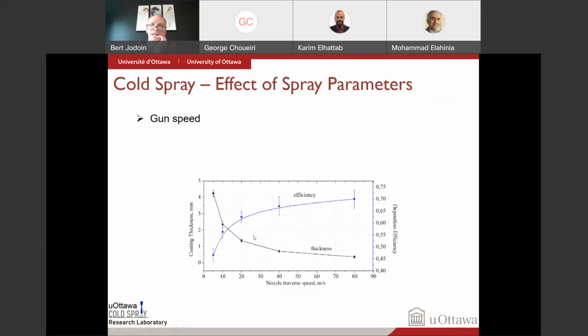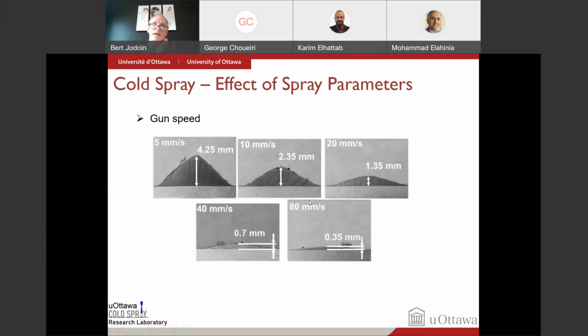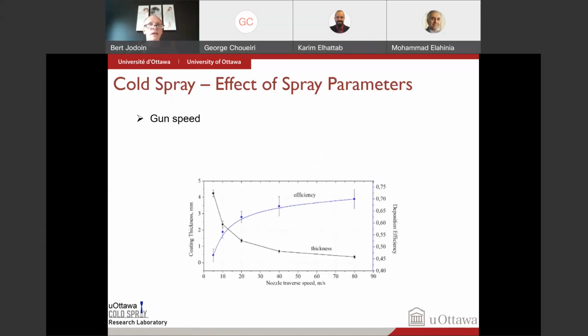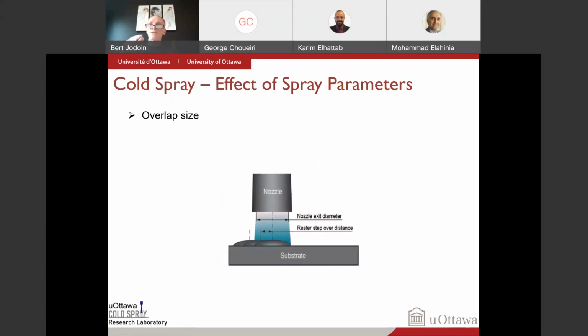This is the thickness as a function of the speed and the deposition efficiency as a function of the speed. The higher the speed, the more efficient that you are. And the reason is if you go too slow, you're starting to build a pyramid. So that means that you're going to start to have particles that will hit a surface that's not 90 degrees. So that's why we try to go with very, very high scanning speed so that we build uniformly to get the better efficiency.